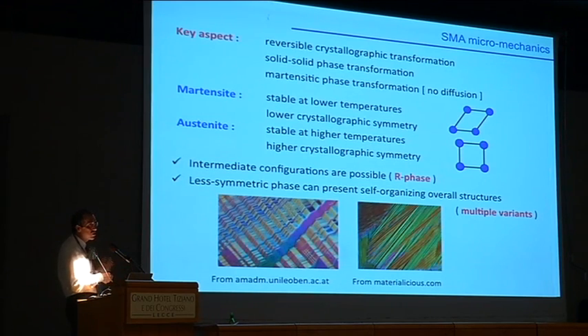Also, if you really want to understand the micromechanics, clearly the complexity is very profound. And just to give you a glance, consider that the material in reality doesn't go from austenite to martensite and that's it. But there are many intermediate configurations which are possible. So there are intermediate phase transformations which may occur. Moreover, once you have the less symmetric configuration, this less symmetric configuration clearly can self-organize in order to accommodate the surrounding conditions, so you can end up with very complex patterns at the microscale.